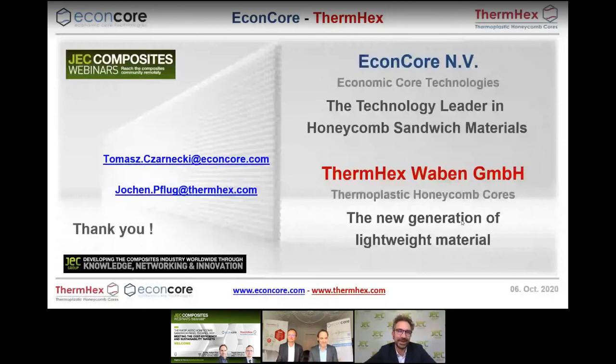Thank you, Jochen and Thomas, for this really insightful presentation. We have a first question from Deepa Jose from Collins Aerospace about the flame performance of the PP honeycomb material — can you share more about FST, smoke, flame, and toxicity? The aerospace industry will require more advanced chemistry than polypropylene. We've done a lot of testing with polypropylene honeycombs for building and other applications requiring fire resistance at different limits. The skin material provides a shield to the core, and the mass of the honeycomb is very low, so heat release upon fire is very limited. But polypropylene is not the material for aerospace. We rather think of polycarbonate honeycomb core, PEI, and PPS. PEI polyetherimide has been qualified for aircraft interior applications and fulfills all fire, smoke, and toxicity requirements.